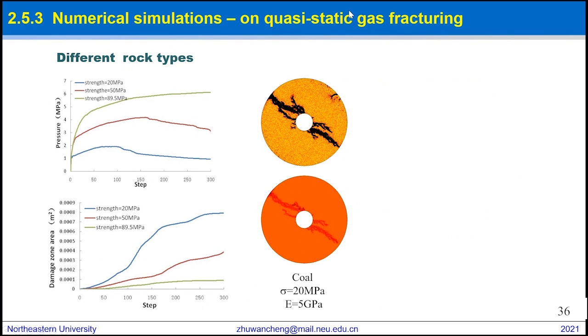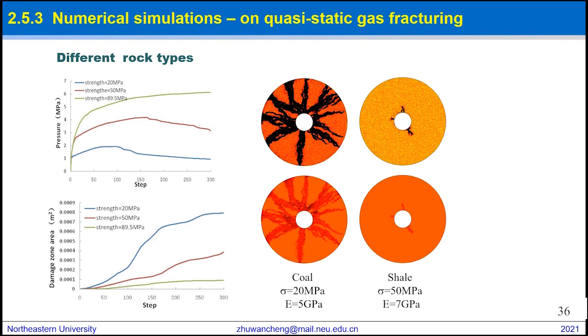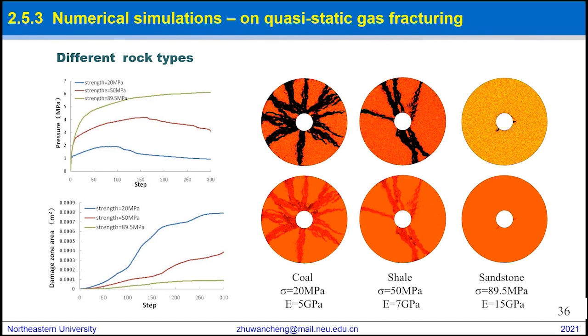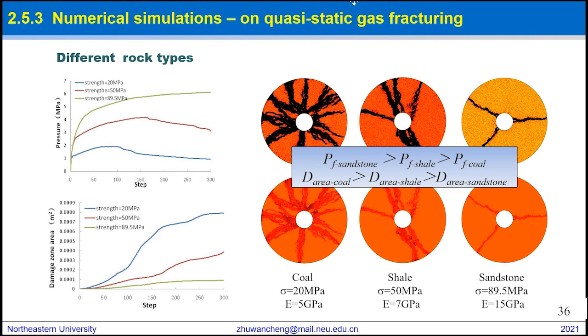Simulation results from gas fracturing in three different rock types suggest that, first, gas fracturing in coal exhibits the lowest breakdown pressure, followed by shale, and then sandstone. In addition, the order of the area of the failure zone is that coal is greater than shale, and shale is greater than sandstone. Second, gas fracturing in coal tends to induce the widest and most complex propagation cracks, with many branches and the most significant local damage, followed by shale and then sandstone.